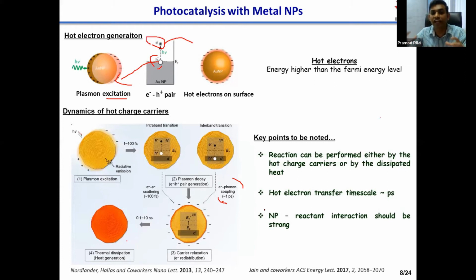In the initial days, people were trying to attach a semiconductor so that the charge transfer can happen to the semiconductor, and that will stabilize the lifetime of the charge separated species. But these days, people are interested to use plasmonic nanoparticle as a sole photocatalyst. And this is where the dynamics of hot electron chemistry is going to play an important role.